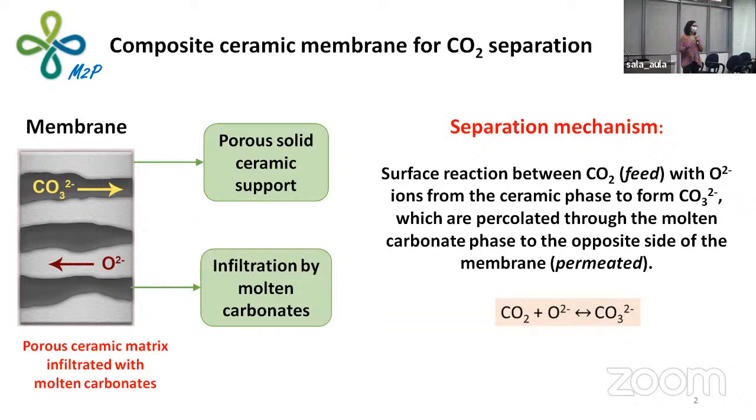So the driving force of this mechanism is the difference of the partial pressure of CO2 on each side of the membrane. And for this reaction to occur, it's important that the flow of carbonate ions be balanced by a counterflow of oxygen ions. So the conductivity of both phases needs to be compatible.